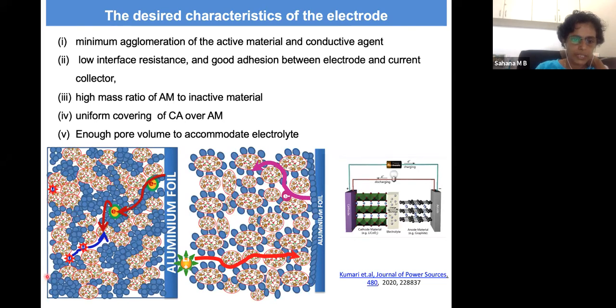So now you can see that these are the representation of carbon black, and these crystals are the active material, in this case LiFePO4. Now, if the active materials are bound together and the carbon black are bound together, and there are very few places where you have pores, then electrons can accumulate in this region. There will not be an electron transfer from the carbon black, which is a conductive additive, to the active material.